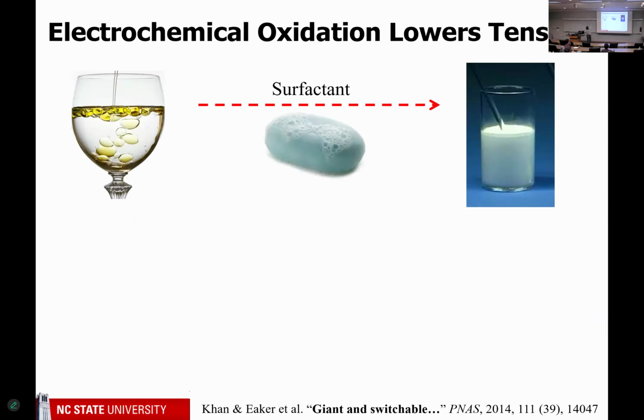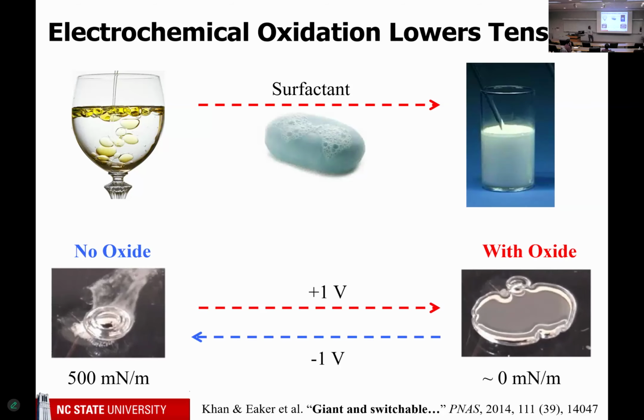And okay, this is not a perfect analogy, but if you wanted to lower the surface tension of a liquid, you would typically add soap. Hopefully all of you have done this today. If not, I probably will not shake your hand later. Anyway, if you have, say, oil and water that don't like each other, you can add soap and that goes to the interface and it lowers the tension from about 70 down to about 30. But in our case, we apply 1 volt, we deposit our surfactant, which is this oxide layer, and at negative 1 volt, we can make it go away. So we can get huge changes in surface tension.